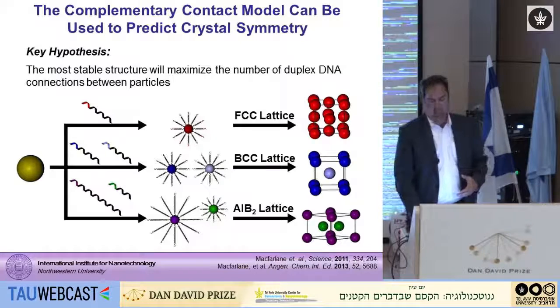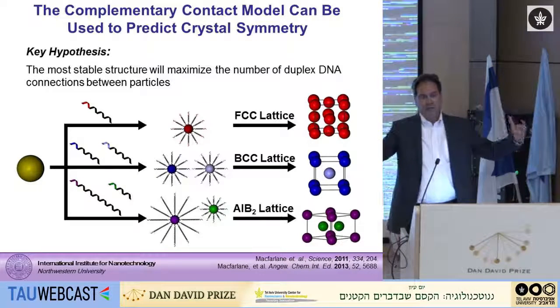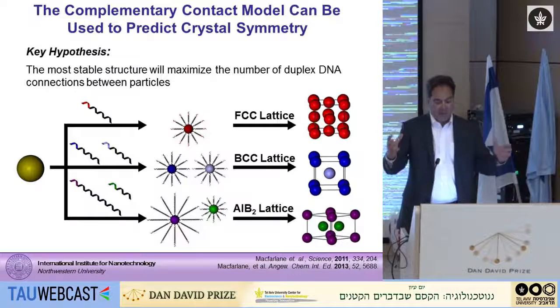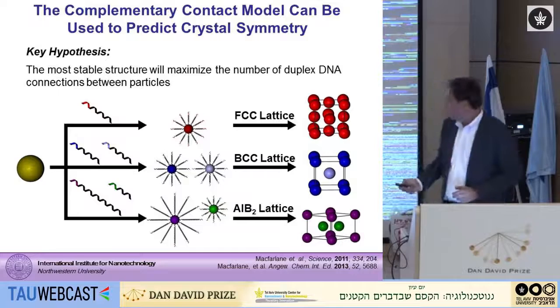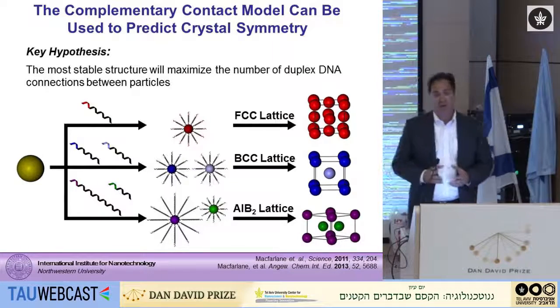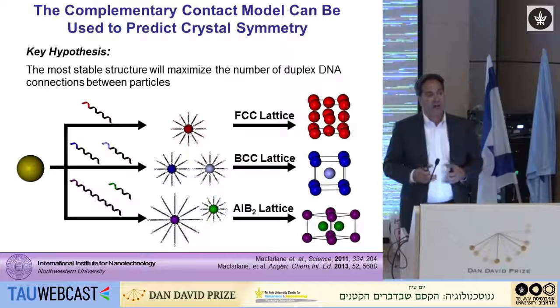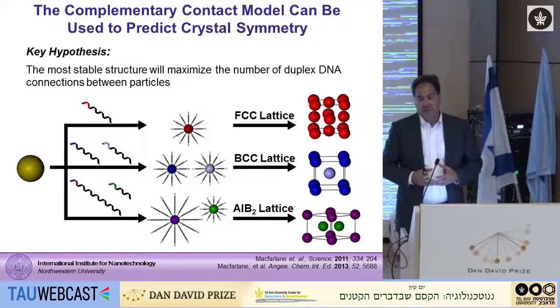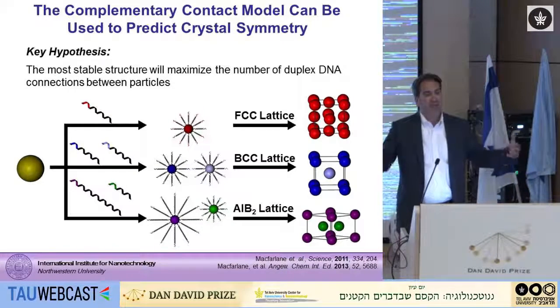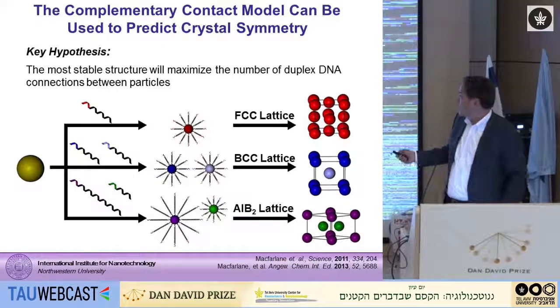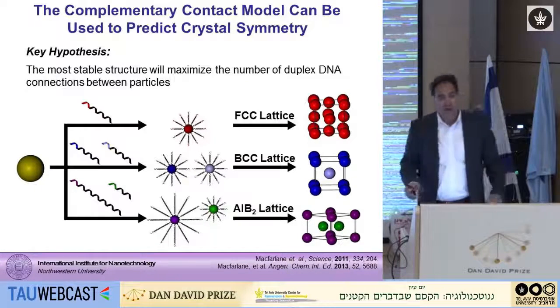Okay, so how do I think about this? Well, it turns out we began to create models, because we don't want to just make spectacular structures. We want to create design rules that allow you to build structures on demand. And we came up with what we call the complementary contact model. The way to think about this is a geometric model where the governing concept is that enthalpy changes, hybridization, is the most important thing in this particular process. It ignores entropy. And it turns out you can do that for greater than 90% of the systems that we're looking at. And what it effectively says is that the most stable structure will maximize the number of duplex DNA connections between particles.